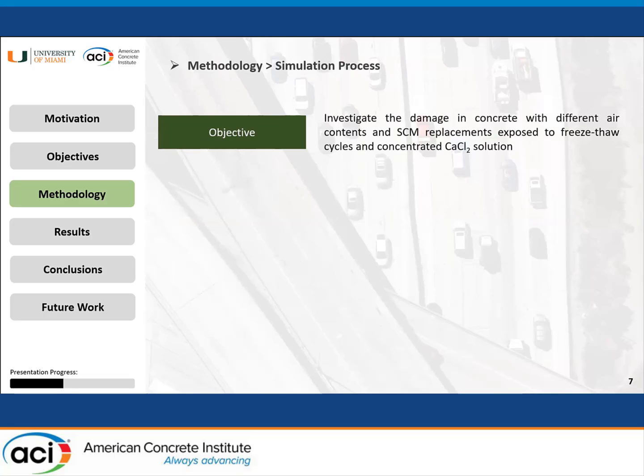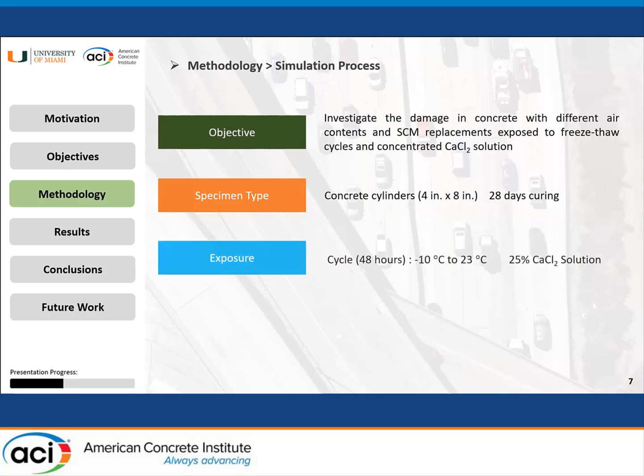So, as we mentioned, the objective was to investigate the damage in concrete with different air contents and SCM replacements when they are exposed to freeze-thaw cycles and submerged into concentrated calcium chloride solution. In order to get to that, we had our concrete cylinders cast with the dimensions of 4x8, and they were cured in moisture for 28 days. The exposure was a freeze-thaw cycle. Each cycle took 48 hours. In the first 24 hours, the samples were submerged into 25% calcium chloride solution inside a freezer, where the temperature was measured to be around minus 10 degrees Celsius. In the next 24 hours, the samples were taken out of the freezer, submerged into the salt solution, and kept in the ambient condition, which was measured to be 23 degrees Celsius.